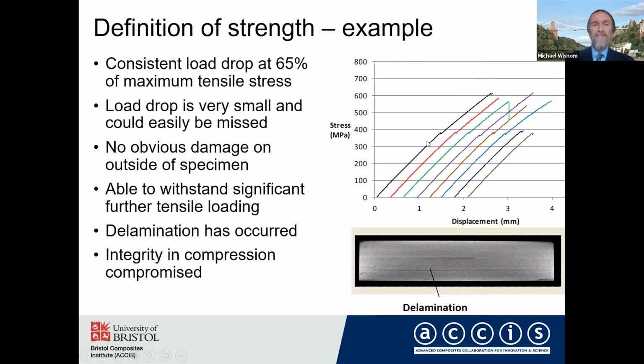About 65% of the maximum tensile stress. It's very small, could easily be missed, and there's no obvious damage to the specimen. And in fact, it's able to withstand significant further tensile loading beyond that. But actually, delamination has occurred, and therefore the integrity of the specimen in further compressive loading will be compromised. So there's a question about which one we should take. Should we take that damage, or should we take the maximum stress?